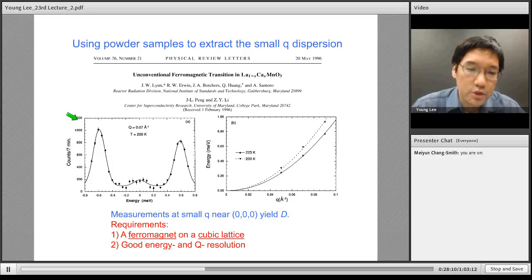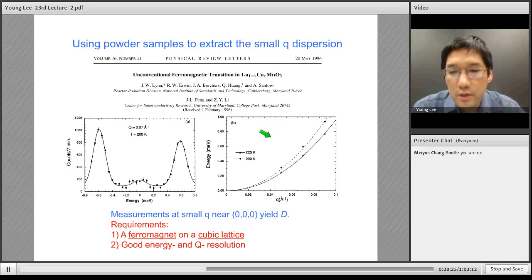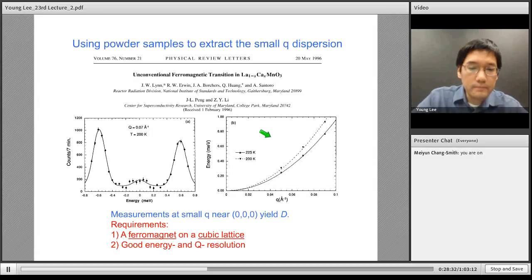And that's what they're showing here. So you see these well-defined peaks in this figure on the left when they stay at some small q, 0.07 inverse angstroms, in scan energy. And then they can even change the temperature in this material and show that the spin wave stiffness changes with temperature. Okay.